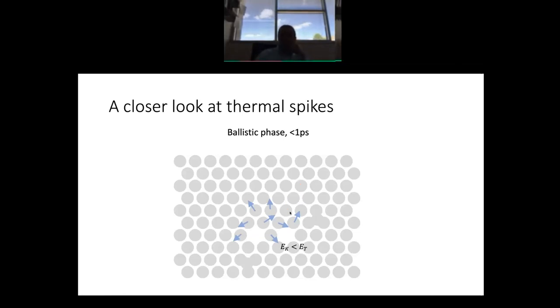So this thing is very interesting. Basically, atoms sort of hit each other sequentially, like a series of billiard balls, and leave behind a vacancy, but the interstitial is created at the end of that replacement collision sequence, which can actually be quite far from the vacancy. So this interstitial atom is not the atom that was knocked out of the vacancy site, it's the terminating atom of that replacement collision sequence. Okay, this will become important in just a minute.